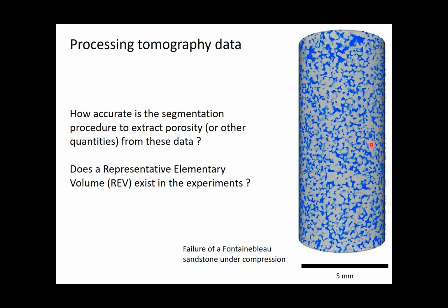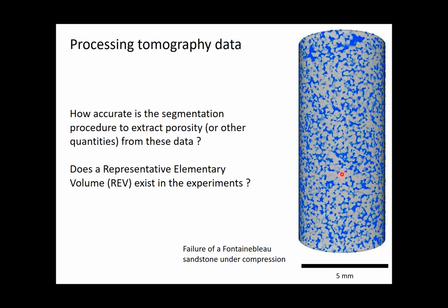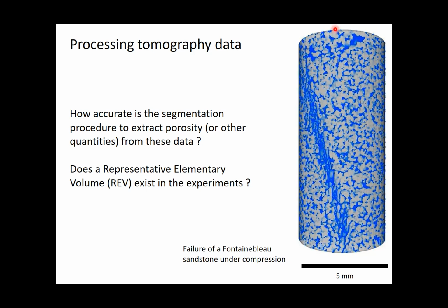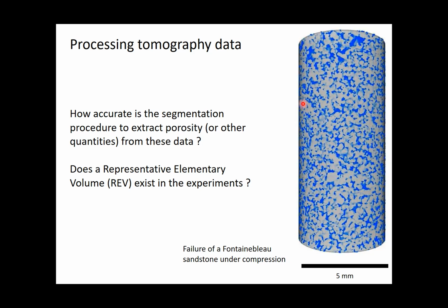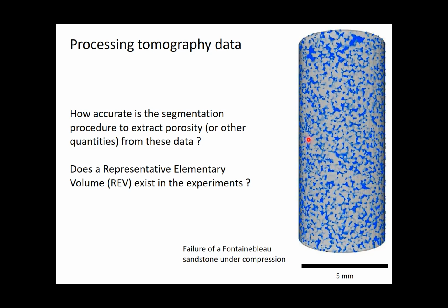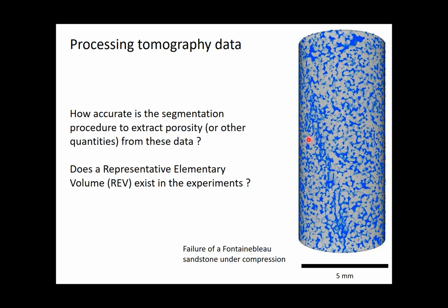So on the right side, it's a piece of sandstone. What is white is a quartz grain, it's a Fontainebleau sandstone. What appears in blue is the porosity. This sandstone is at 20 MPa confining pressure, and the stress is applied from the top, the bottom is fixed. As the stress is increased, you will see two conjugate faults start to develop. We can image the development of this network with synchrotron imaging. And that's the data we have.